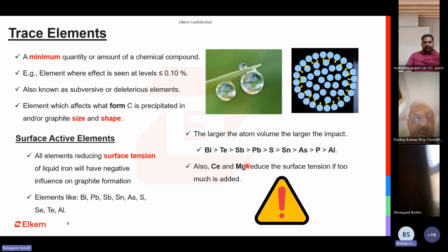So this is with respect to trace elements. The definition of a trace element is how much of it should be present to damage the precipitation of carbon as either graphite or carbide. In spite of it being precipitated as graphite, we are happy, but it can also influence the shape and size of that particular graphite. This is also called a trace element. All trace elements can be either good or bad. Most of the time, the bad trace elements tend to be surface active elements. What do I mean by surface active elements? It plays with the surface tension of the liquid iron. It spoils the shape of it, which can be a benefit, which can also be a problem. 80% of the time, it is a problem. The benefit out of it is very less. We will discuss this going ahead.